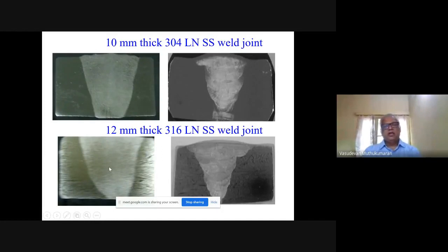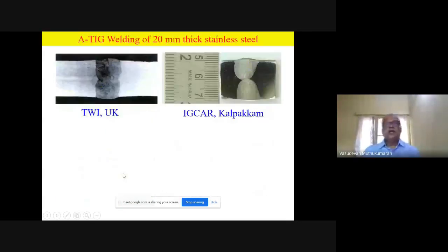Then the bottom one is 12 mm thick 316LN. On the right side is multi pass, 13 passes, which we could do in a single pass. The properties are very good. We were very happy, and that's why we pursued this process. Internationally, TWI also has developed this process. They have demonstrated double sided 20 mm thick. The same thing we tried here, and we could also get 20 mm. You can see here, using the same system I mentioned.